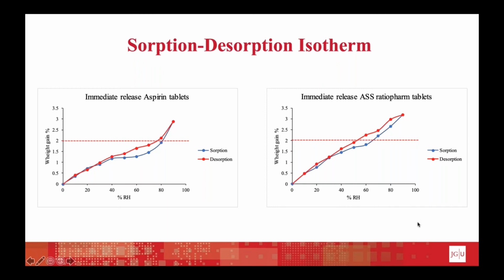And this chapter describes that when the weight gain at 80% relative humidity, so at this point here, for example, is above 2%, but lower than 15%, our material is hygroscopic. If it's above 15%, then our material is very hygroscopic. And when it's below 2%, but above 0.2%, our material is slightly hygroscopic. So when now looking at our two tablet formulations, we can see that the ASS Ratiopharm tablets are hygroscopic, whereas the aspirin tablets are only slightly hygroscopic.